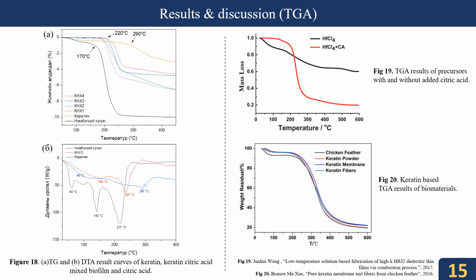So next, keratin-citric acid mixed biofilm and citric acid thermal analysis were performed by thermogravimetric analysis. As shown in figure 18a, keratin-citric acid biofilm undergoes two weight losses. Keratin undergoes slight weight loss due to moisture evaporation at 116 degrees Celsius, and maximum weight loss begins at 219 degrees Celsius. For citric acid, the maximum weight loss occurs at 170 degrees Celsius, which is a lower melting temperature than the keratin degradation.